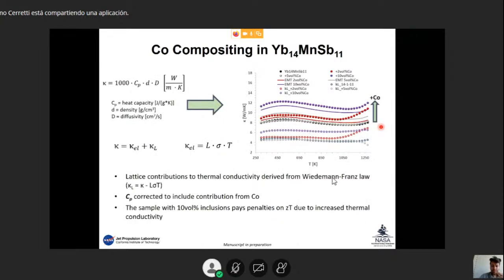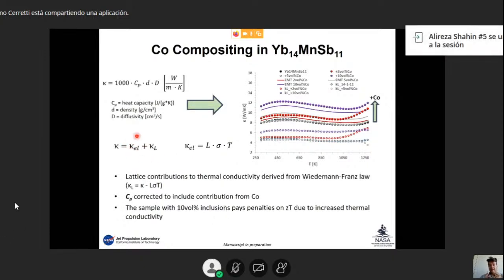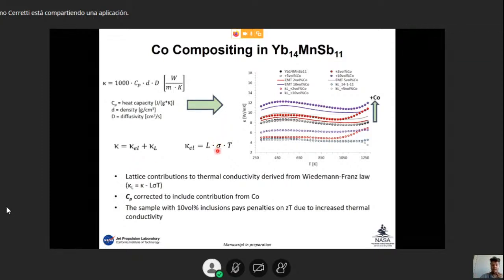At that point, the next step was to analyze the thermal properties. We can see that for the 2 and 5%, they are still in line with the same value of the pure ytterbium manganese antimony, and instead the 10% showed an increase over the whole temperature range, which is due to the increase of the electronic contribution because it has a better electronic conductivity. Therefore, this parameter is higher.